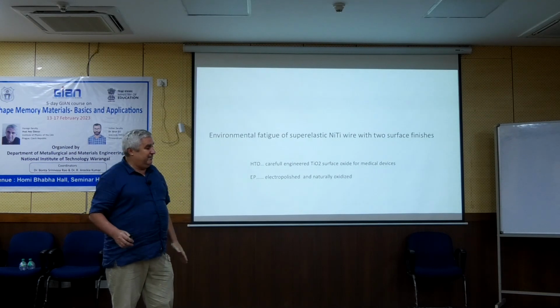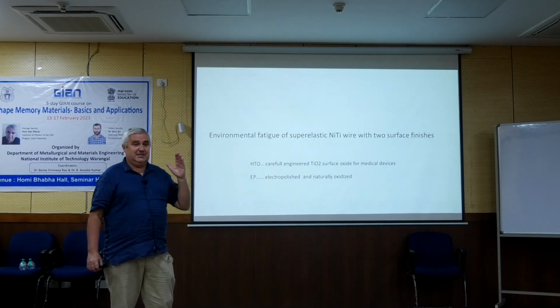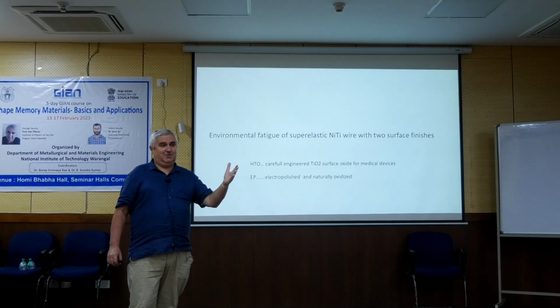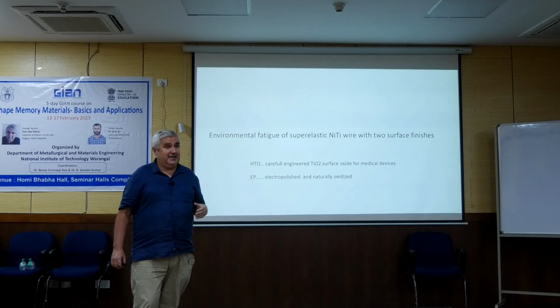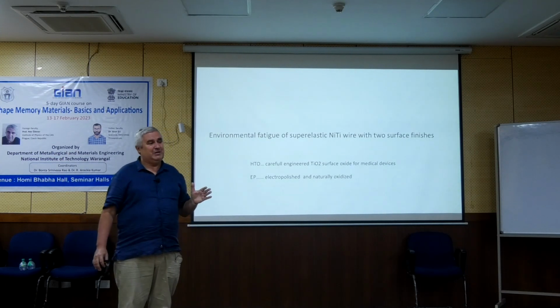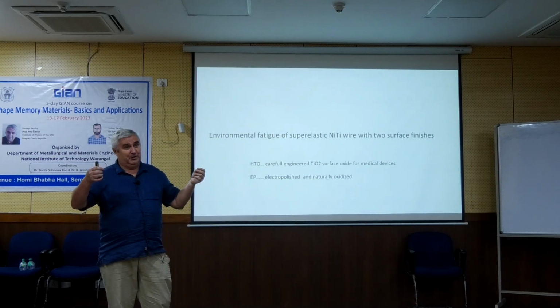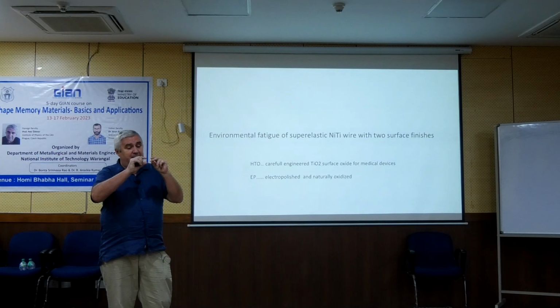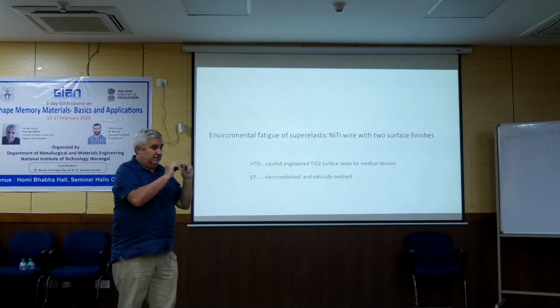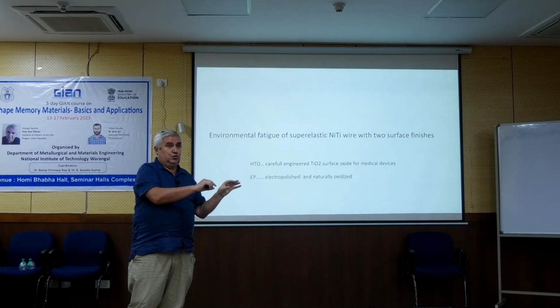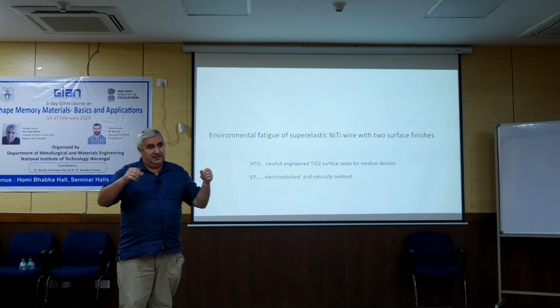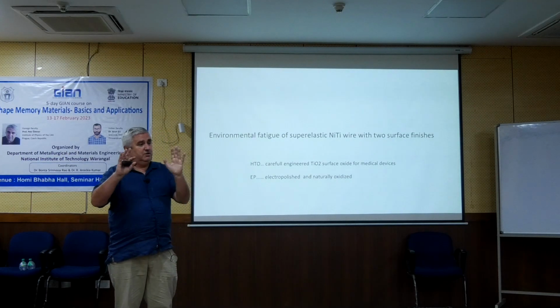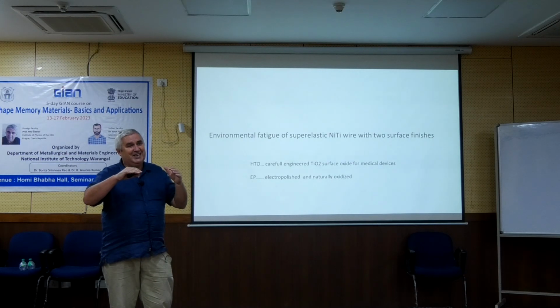But finally, one of these companies gave us their number 1 wire, which they said is the optimized oxide. So maybe they use something like you said, but I'm almost sure they didn't do it, because for them this would be very difficult processing. What they do is make the oxide as thin as possible in such a way that if they put it without any stress into the material, it shows good corrosion properties. When they stretch it, they don't test so much, they don't care about fatigue, they care more about nickel leakage.